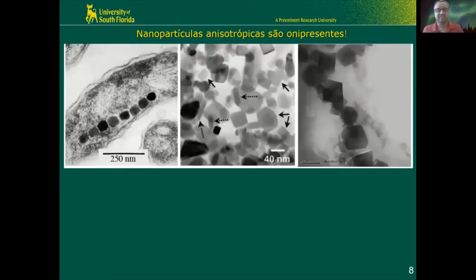These are transmission electron microscope images that many of you, obviously, if you're working in nanoparticles, take to an electron microscope and look at with a TEM. So what you're seeing here are three images, 1, 2, 3, and they are the same material. They are Fe3O4, magnetite, spinel ferrites. It's the same material, but the source of these nanoparticles in these images is what makes them interesting, okay? Let's look at the first one here on the left.